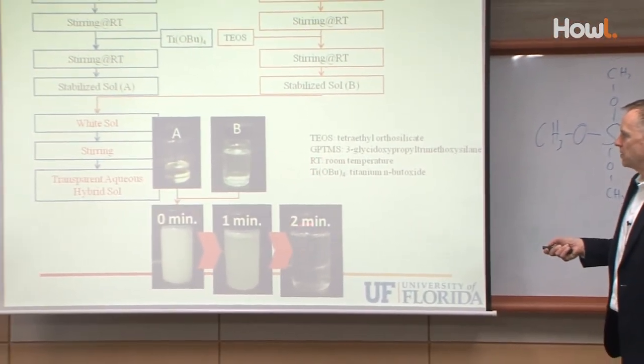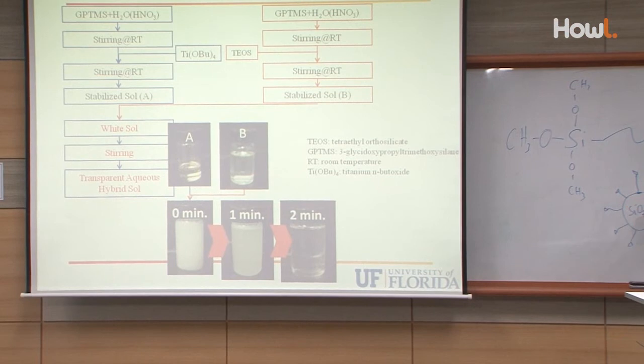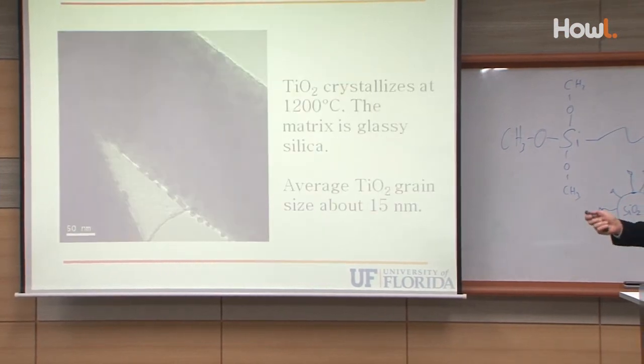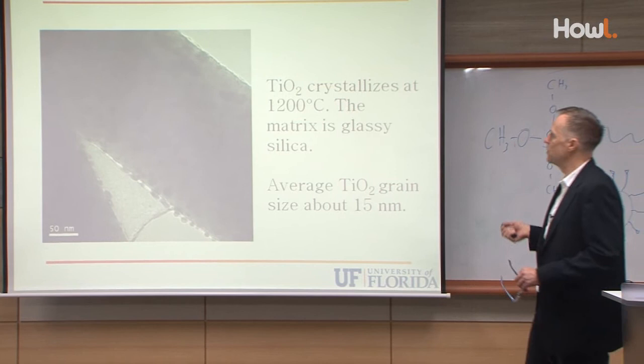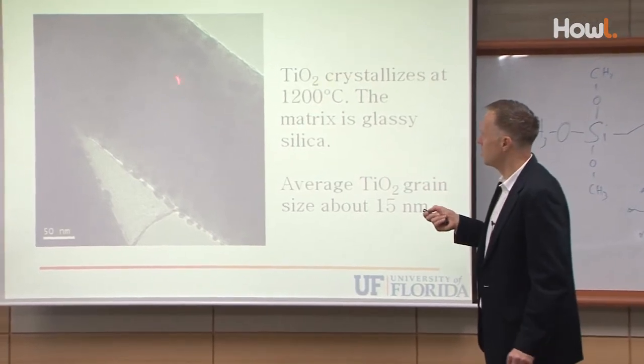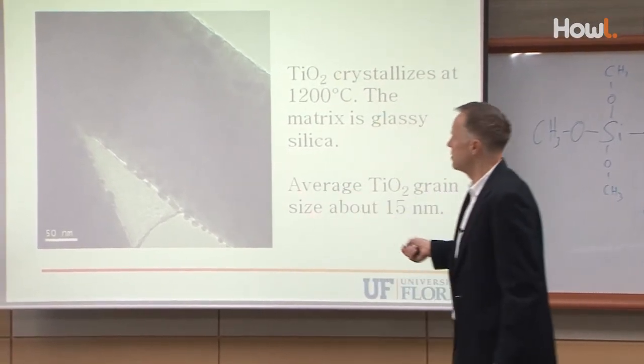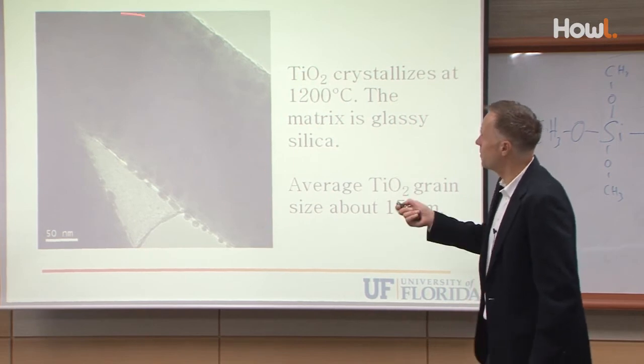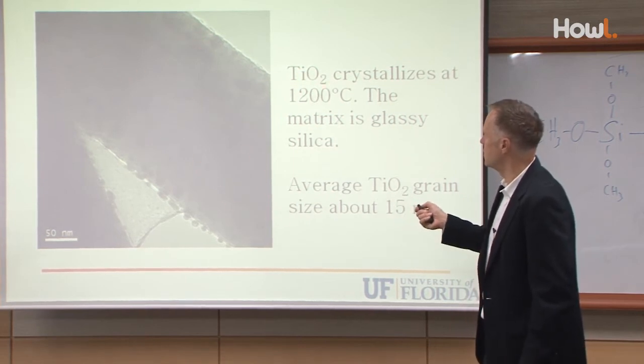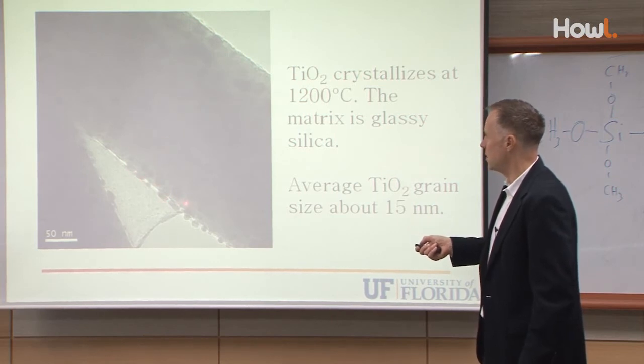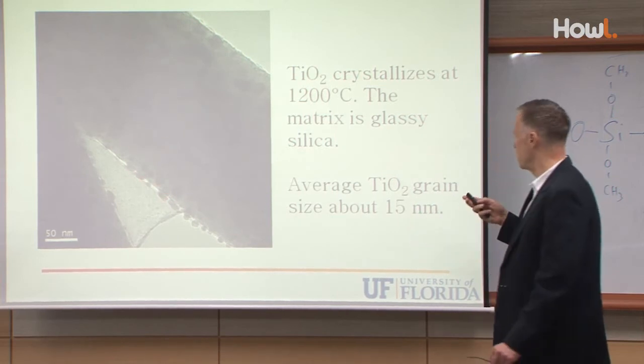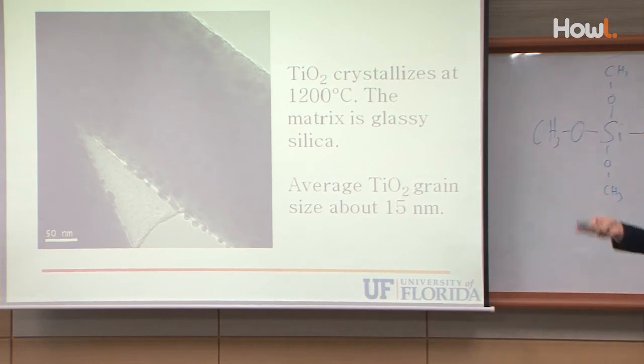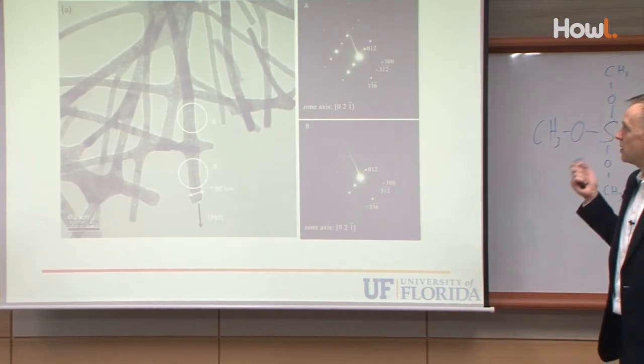Now you can also combine it with other compounds like titanium butoxide, and everything gets into a system that is then colloidally stable like this. And when you electrospin them, you come finally to systems where it's very difficult to see. These are dense fibers of silica, and on crystallization at 1200 Celsius, you find titania particles, for example, in it, but you can do it also with pure silica or combine it with some other compounds. That's an interesting thing.